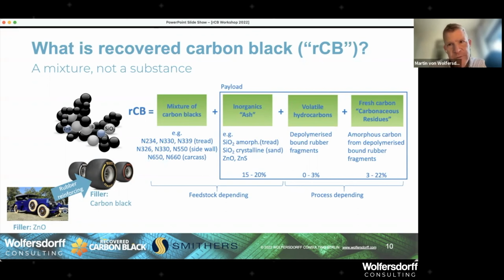But when you mill the recovered carbon black, and the milling trend is to ever smaller particles, now we're talking less than 10 microns, 10 micrometers, then that means that the crystalline silica is milled to the same particle size, and that at that particle size, it becomes respirable crystalline silica, which is a toxic substance. Also, zinc oxide and zinc sulfide.